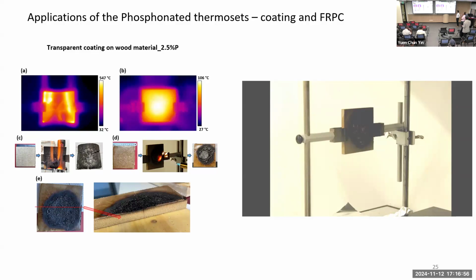We did not continue this test, but once you form this barrier, it more or less can shield the inner layer very well. So I would assume just from the flame itself, it would be able to easily withstand for a long time, hours. But at one point, we did not do this test, and this is not a standard test. This is just a, what do you call it, advertisement test, there is no standard associated. If we have to look into real applications, we need to look into the standard test methods.